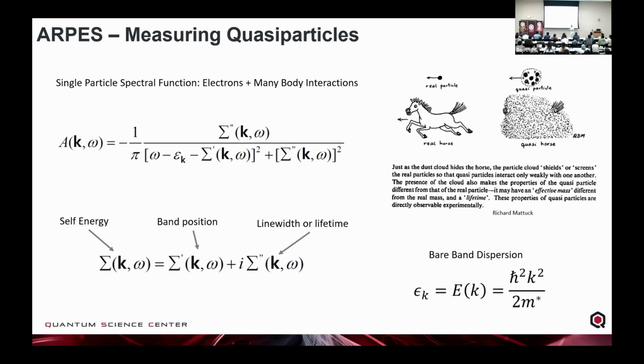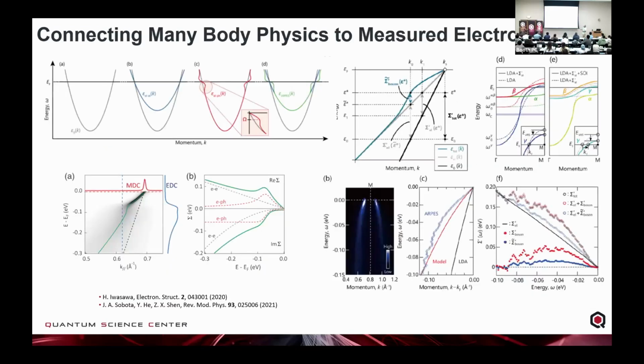And so now it will behave sort of like an electron, but it could have a different mass or a lifetime based on all of these many-body interactions happening inside. And so this is what we directly measure with ARPES. We can see signatures of all of this evidence in there. We have the bare band that you can calculate with DFT. A lot of the electron-electron interactions could change the bandwidth. If you have electron-phonon interactions, at the energy of the phonon you can see these kinks.